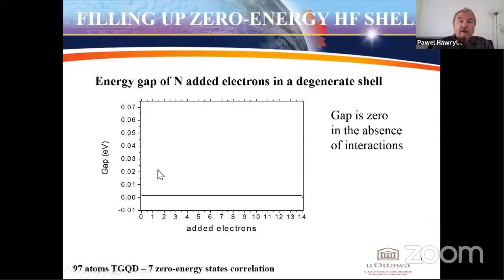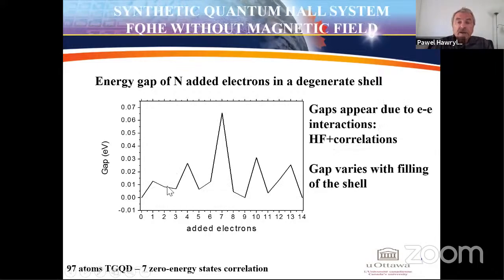So here, if I am adding electrons into the degenerate shell and there are no interactions, the gap because of the degeneracy is zero. So nothing is visible here. And if I turn on interactions, I see that the gap oscillates just like in fractional quantum Hall effect. And so gap varies with filling of the shell. It's largest at half filling, and this corresponds to a magnetic moment of this graphene structure.